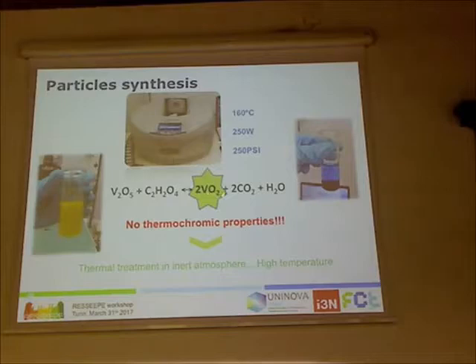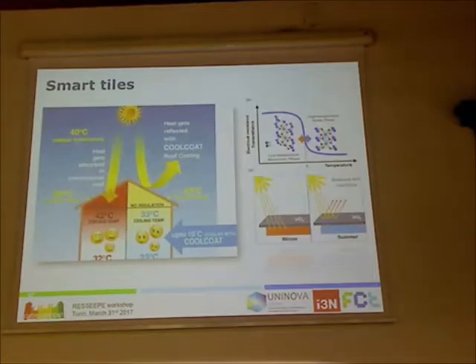But you need to be careful, because if you do this in an oxidizing atmosphere, you will transform the VO2 into V2O5, and you lose the transition temperature at 68 degrees. So this needs to be very well controlled to get the stable phase while keeping it intact for the thermochromic property.